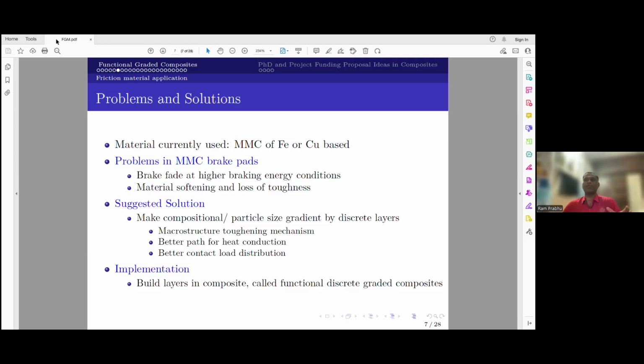Looking at the copper or iron based brake pads, the biggest problem, as I said, is that at high energy and high friction, huge temperature is generated. So there is oxidation at the interface, which leads to brake fade, meaning loss of coefficient of friction. In other words, I need a longer stopping time or stopping distance to stop the aircraft. It is nothing but the loss of braking effectiveness. And higher temperature also softens the material and affects the life of the brake pads.